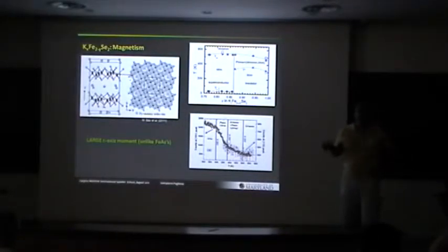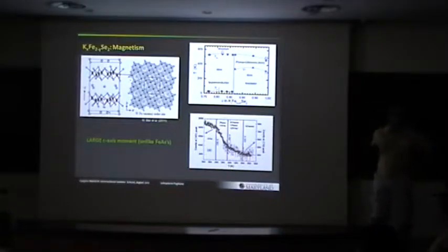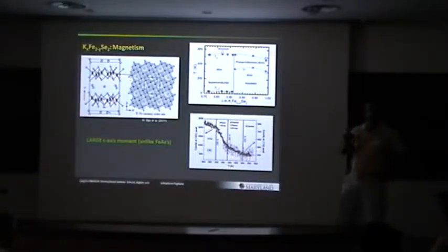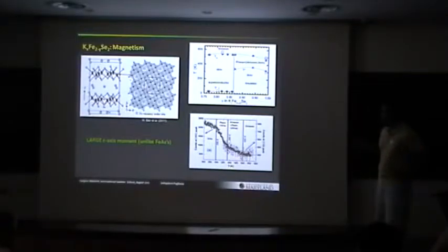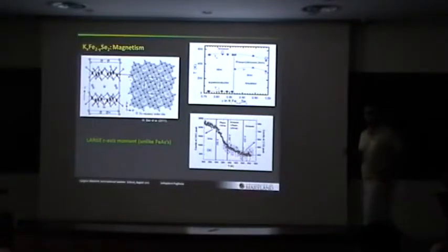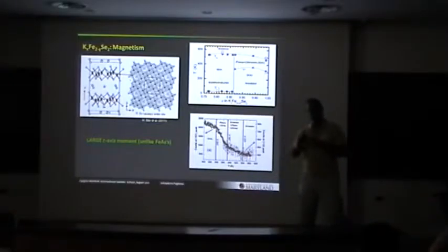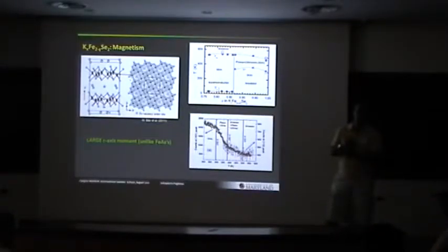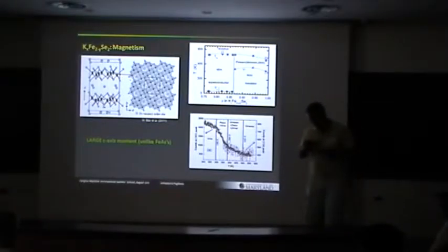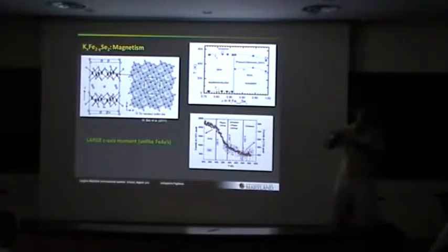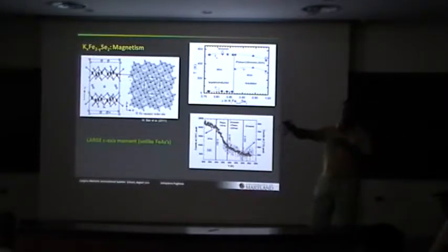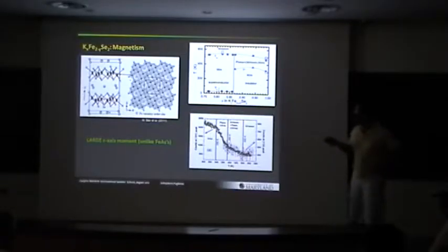Okay, so regarding the magnetic order, the other peculiar thing about it, other than it being a 3 Bohr magneton staggered moment, is that the moments are aligned along the z-axis. This is much different than all the other iron arsenic and iron chalcogenide materials, which have staggered moments with Q vectors that are predominantly in the plane, more or less commensurate and looking like nested vectors with the Fermi surface. So here you have c-axis moments.